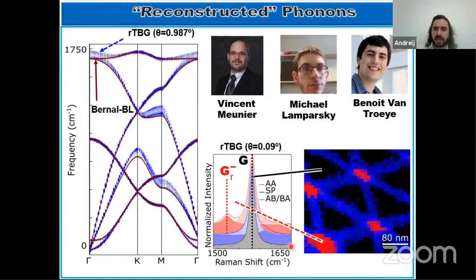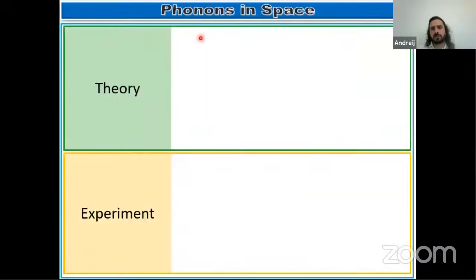When we go to the AA site, we see a new peak showing up at the left of the G peak, which we name GR minus. But for the SP, we see another new peak at the right of the G peak that we call GR plus. And look, these are similar to what the theorists observed. And the similarities do not stop here.